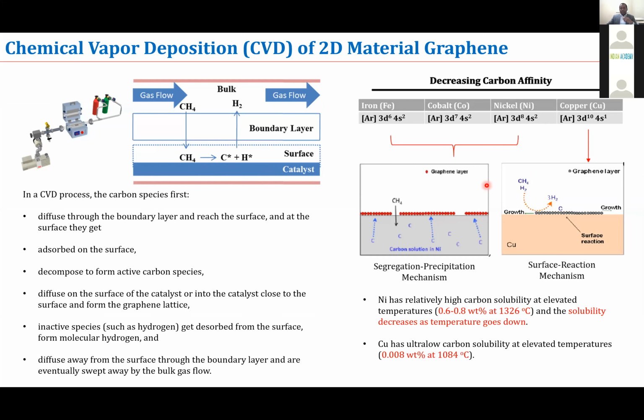In the case of nickel, you can see here, nickel has a high carbon solubility. At higher temperature, the carbon can diffuse into the nickel while the growth is happening. Then as the cooling starts, carbon atoms diffuse out from the nickel and form graphene. The amount of carbon that is diffused into the nickel should come out, so we need to control the cooling process. Cooling has to be fast so that the carbon atoms can come out. However, there is a possibility of producing multiple layers of graphene.